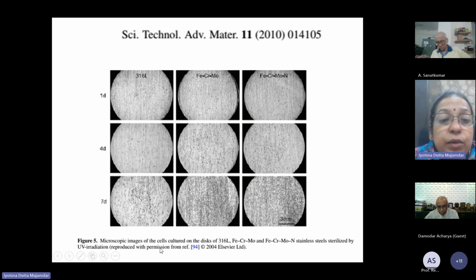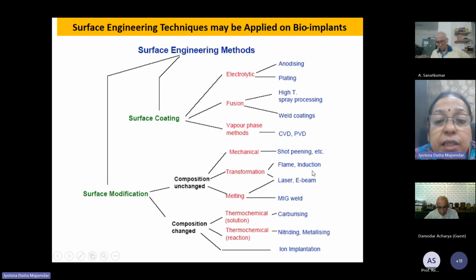So again, this is showing how the cell is growing after 7 days. It is not visible over here, but if you see the report over here, it is shown that for nitrogen containing steel, the cell viability and proliferation rate is higher than that of other 316 stainless steel.